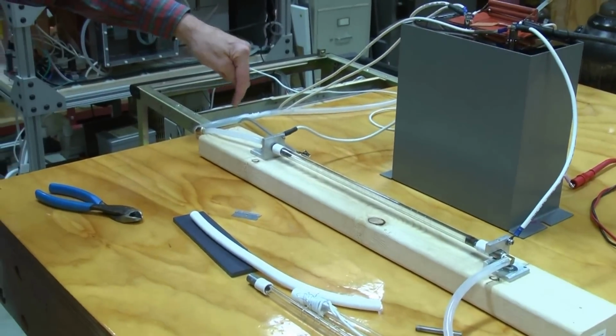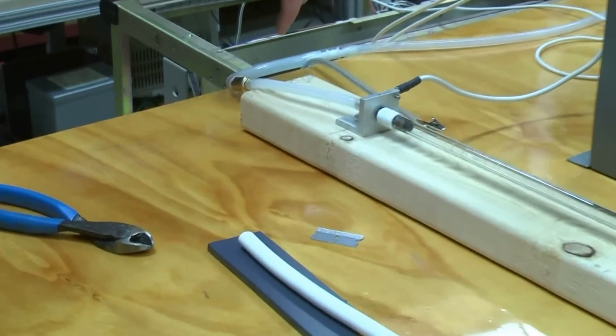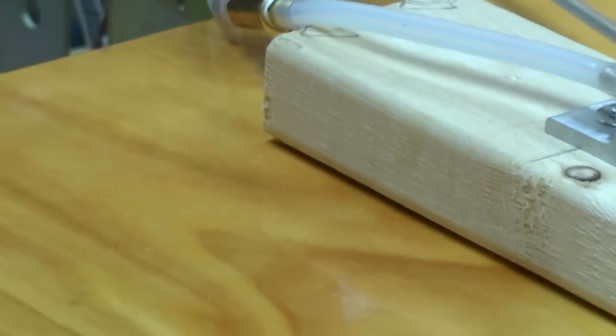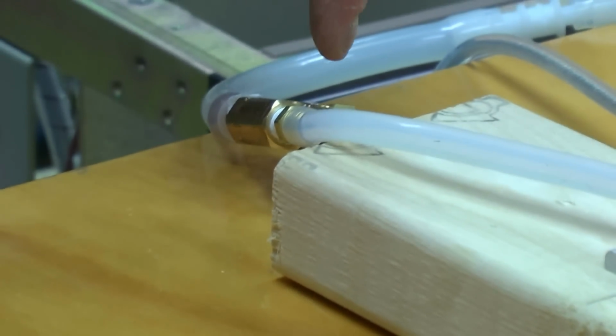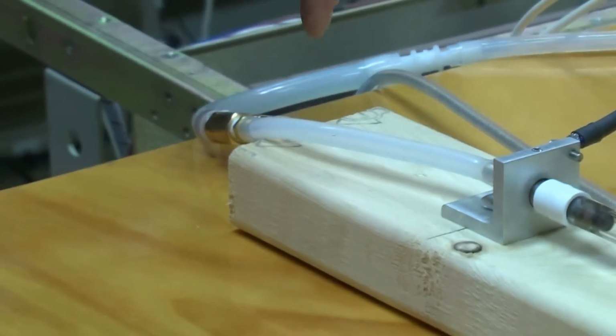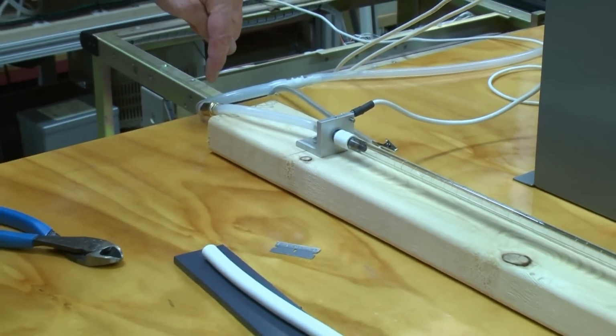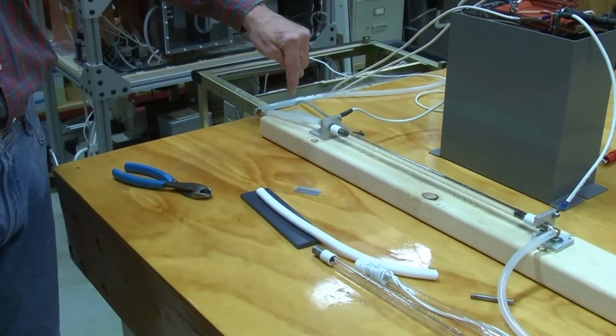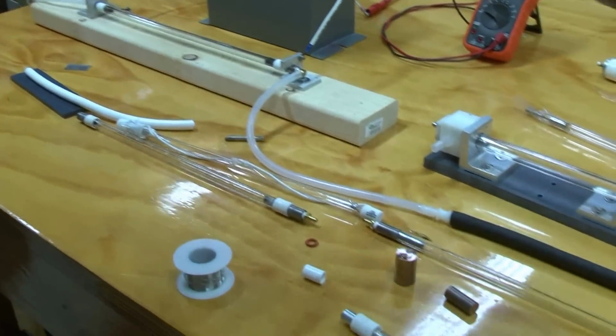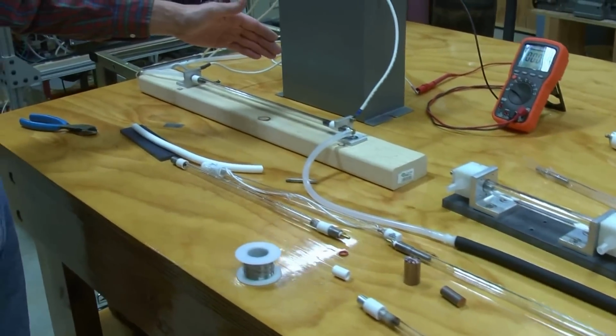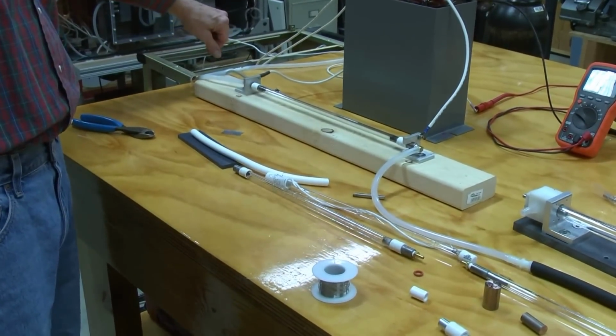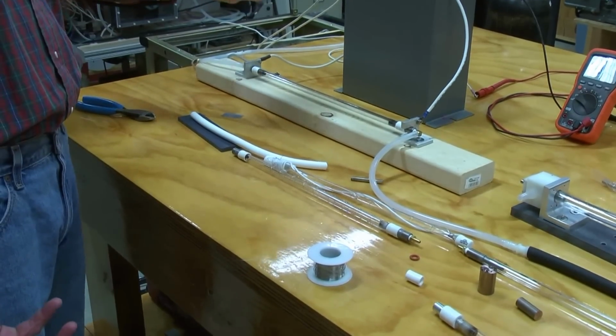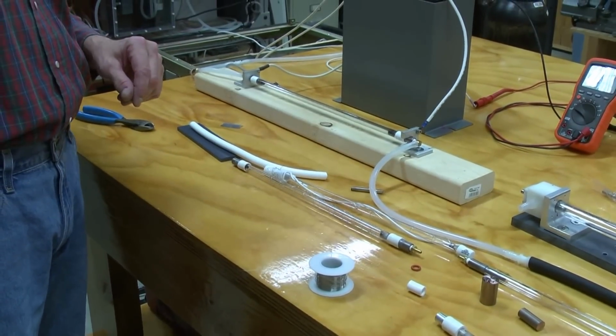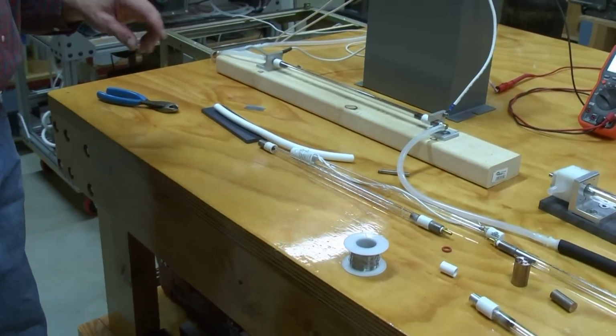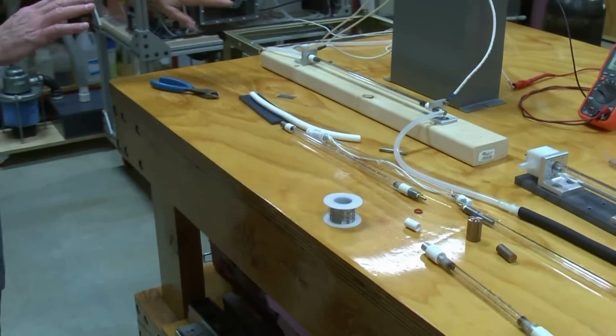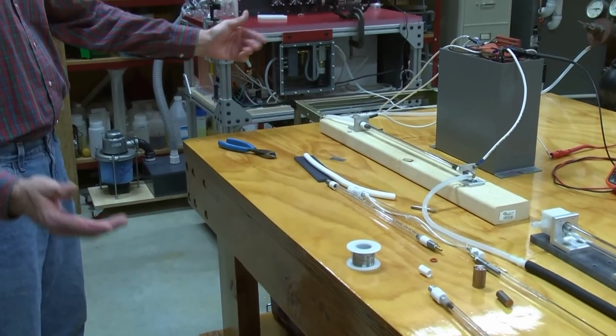This is a fairly special component. It's a 0.02 millimeter square area needle valve, so very, very small area, with a 20 turn adjustment. Very fine adjustments are necessary because what you're trying to do is allow a very tiny leak into a free open vacuum system that would normally go down to about 1 torr. But when you add the leakage, you can bring the pressure up slowly to whatever pressure you need to just hold off the capacitor. So I'm going to show you with this thing not even cracked, so it's just about 1 millimeter,